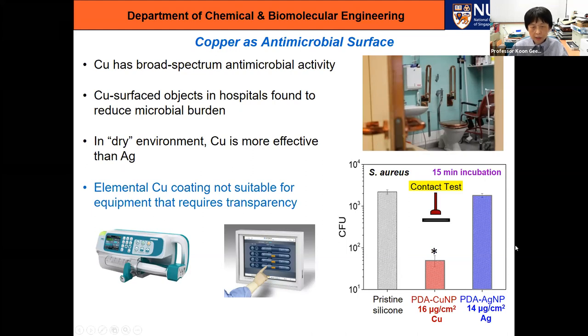As you can see from this test, in this test is what we call the contact test. We contaminate this stud, this brown stud, with bacteria, and then we press it against the surface to simulate touch. And then we see how many live bacteria was transferred over after a certain incubation time. So this is silicone surface. After 15 minutes incubation, we detected 2000 live bacteria.